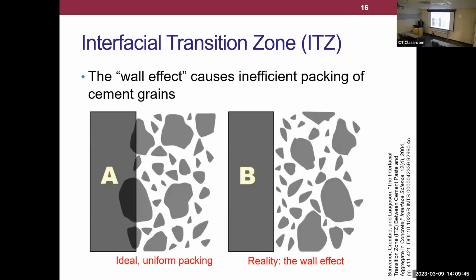So what we did then is we looked at something known as the interfacial transition zone. This is the ITZ that forms in concrete due to something called the wall effect. In a concrete, the aggregate basically looks like a wall relative to your cement grains. Cement itself also has a gradation, a very, very fine gradation, with a mean particle size of about 15 microns.